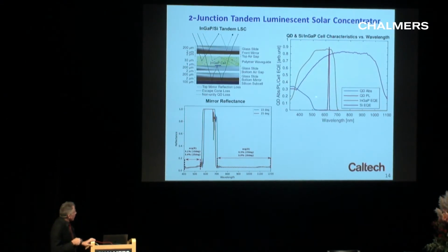So this shows the cross-section of the waveguide, the absorption spectrum of the indium gallium phosphide solar cells, and the absorption spectrum of the quantum dots. They absorb in the blue, they luminesce in the orange, but they luminesce such that they're absorbed in the indium gallium phosphide. The silicon does the work of power conversion from the red to the infrared.